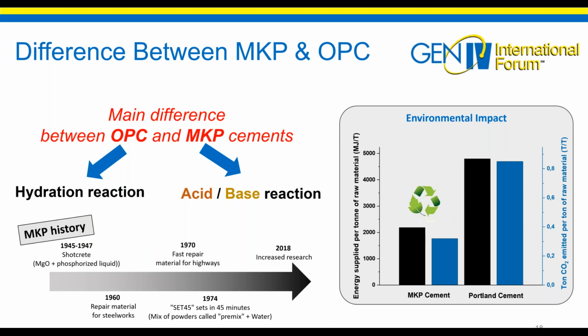We can wonder what is the major difference between Portland cement and phosphate cement. The answer is very simple: it is the reaction mechanism of setting. In the case of Portland cement, it is a hydration reaction, whereas in the phosphate cement matrix, it is an acid-base reaction. Another difference between these two materials is the environmental impact. As the phosphate matrix requires less energy than the Portland matrix, this difference impacts the amount of carbon dioxide. The quantity is 3 times less in the case of phosphate cement. This difference makes the phosphate matrix an eco-responsible material.